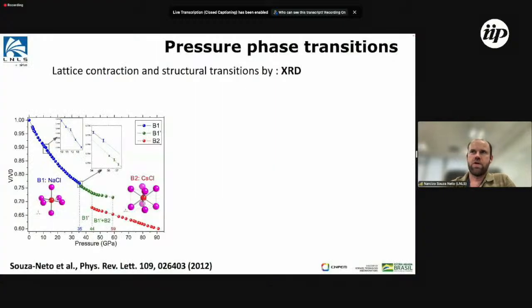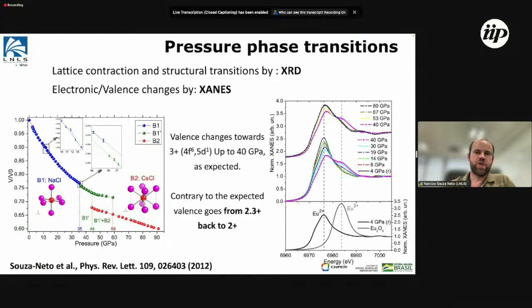How we do that, one example is here, where we are looking at pressure phase transitions. We can look with X-ray diffraction, which is one technique that we use, at how the unit cell volume changes with pressure. And there are structural phase transitions that are related to electronic changes as well. This one is not structural, it is more of an electronic instability, and this is structure. Also, we can combine that with spectroscopic techniques to look at not only the atomic structure, but also the electronic structure,